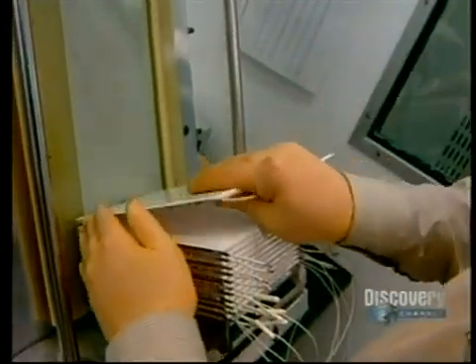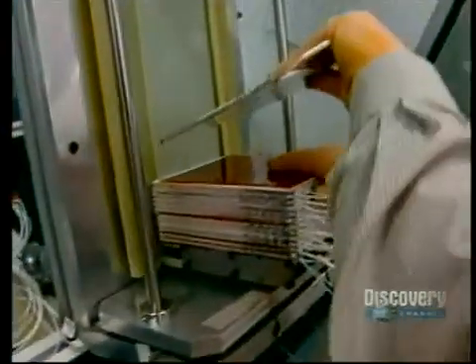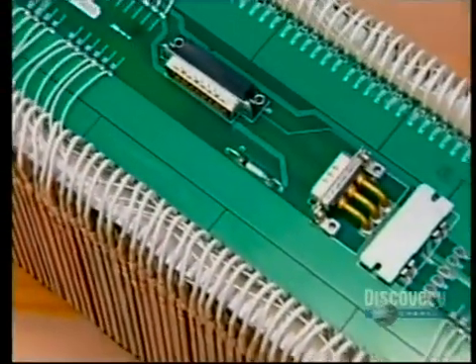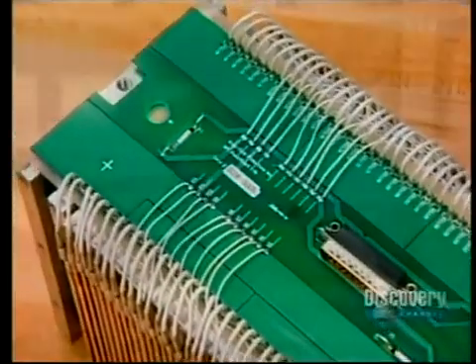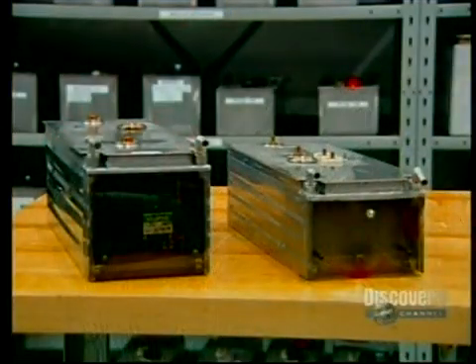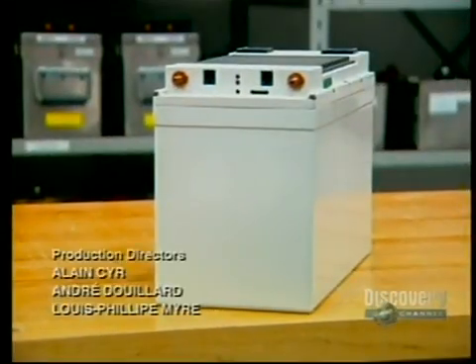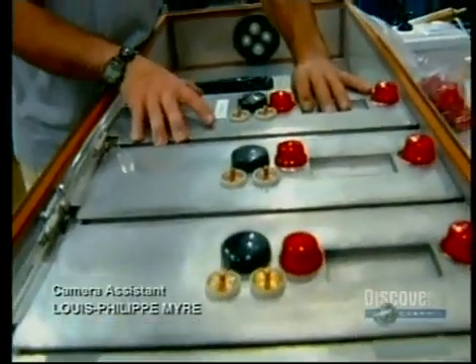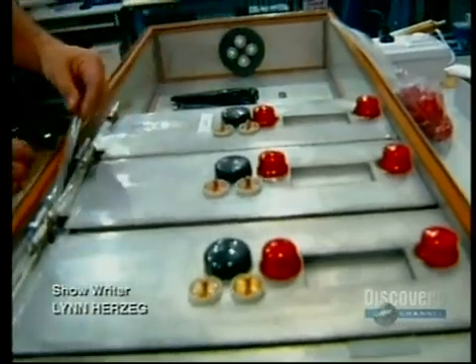The cells are isolated with foam so that they do not touch each other. These red sheets are actually heating elements, since the lithium metal polymer cells function at temperatures of between 104 and 176 degrees. Here we see the modules of the battery pack for a hybrid vehicle — an automobile that works with both a gasoline-powered motor and an electric motor.